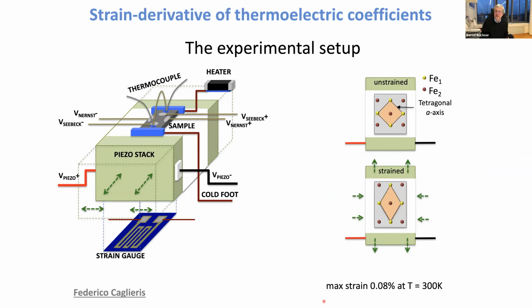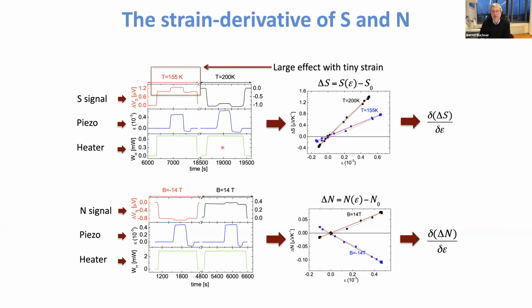And the strain which we can apply here is tiny, 0.08%, but it's still sufficient to see a signal. And that's shown here, just an example. So that's the way we do these measurements. So we switch on a heater. The heater induces Seebeck, the thermal power. So you see a voltage. Then we switch on the piezo and you see a change of the Seebeck effect, switch off the piezo again and the heater. So that's then the strain dependence of the Seebeck effect.